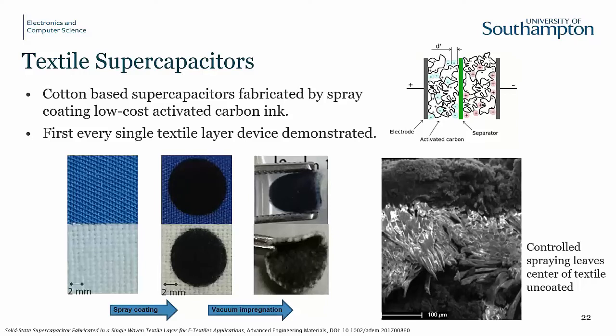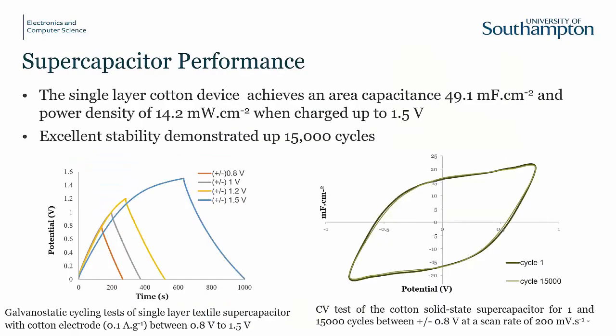And then we use a spray coating process, which we control so that the ink or the solution is only absorbed a certain depth into the textile. If you do that from both sides of the textile, you can leave a region uncoated at the centre, and that acts as your separator. Using this process, you can take any standard textile and make it into a supercapacitor. And in terms of performance, it's very effective.